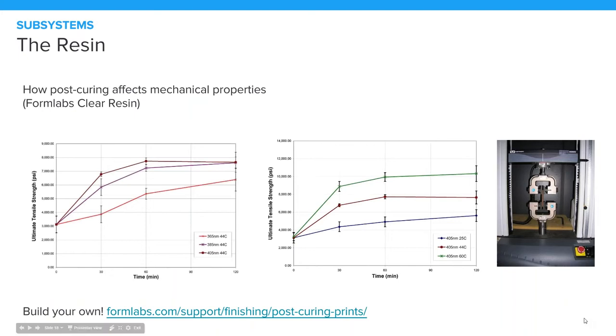One key thing that we recommend for all users to investigate is a good post-curing solution for their prints. Really, after the print, the polymer is still not fully reacted. There are still lots of little reactive groups hanging around, and the polymer is still technically considered to be green. By post-curing that polymer, we are completing that polymerization process to a much higher degree, which makes it much stronger and less sticky. The charts on this graph are measuring tensile strength, which is the resistance of a material to breaking under elongation.